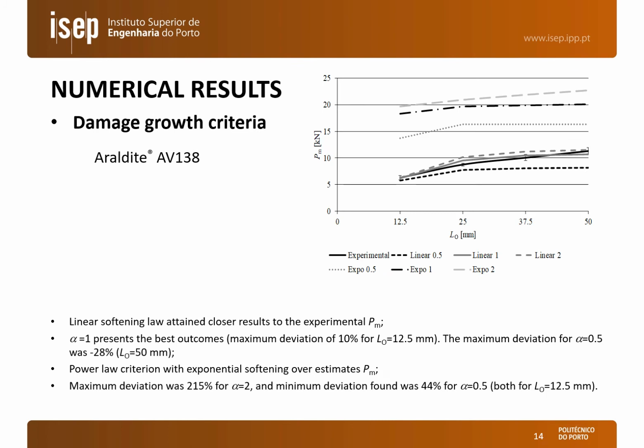Regarding the damage growth criteria, we present here the results for the AV138, and we are going to consider both a linear and an exponential damage law with different damage exponents. We can see that the linear softening gives closer results to the experimental maximum loads. Regarding the exponent, 1 presents the best results, with a maximum deviation of 10% for 12.5 millimeters, and the deviation for the exponent of 0.5 was almost 30%, as we can see in the figure.